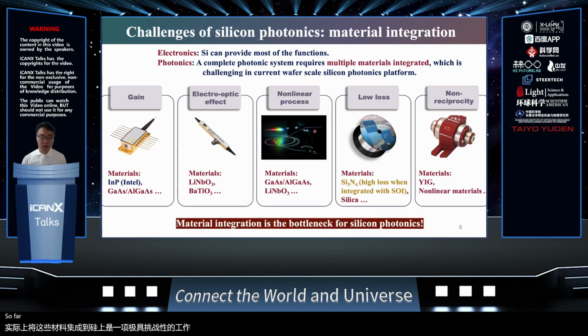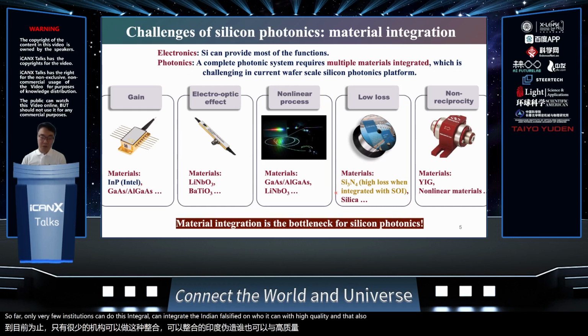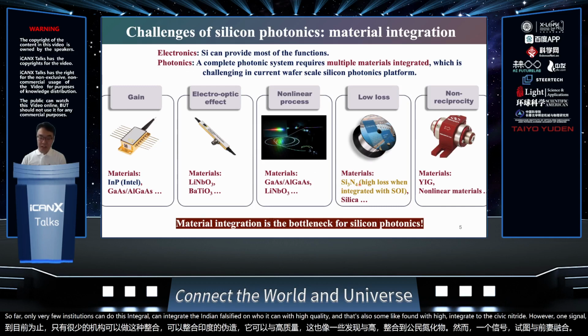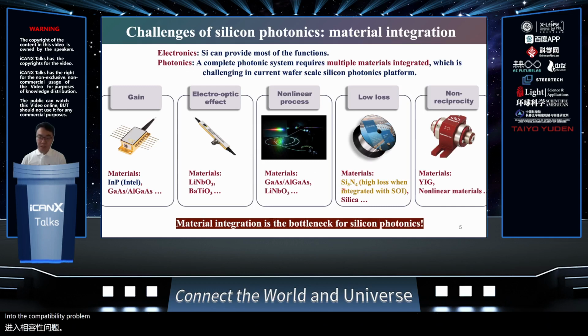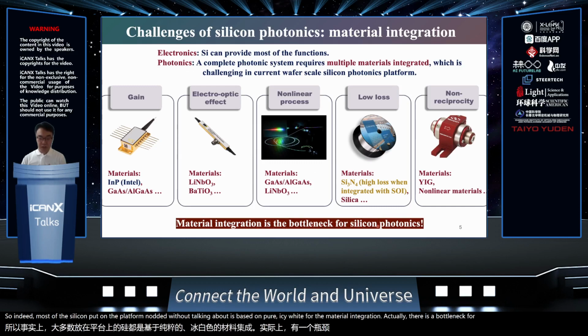So far, only very few institutions can do this. Intel can integrate indium phosphide onto silicon with high quality, and some foundries can integrate silicon nitride. However, once silicon nitride gets integrated with SOI, due to compatibility problems, they couldn't really deliver the low loss they should have. So indeed, most of the silicon photonics platforms we are talking about nowadays are based on pure SOI. Material integration really is the bottleneck for silicon photonics.